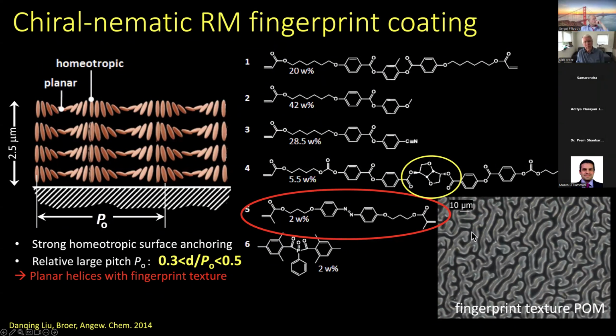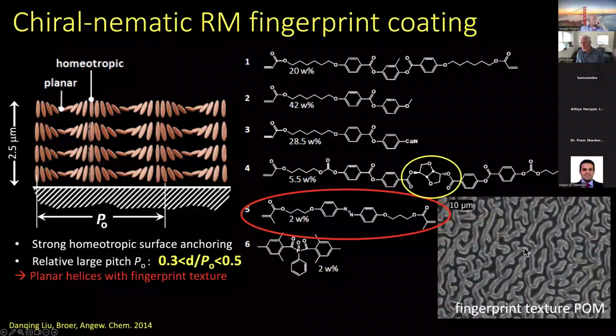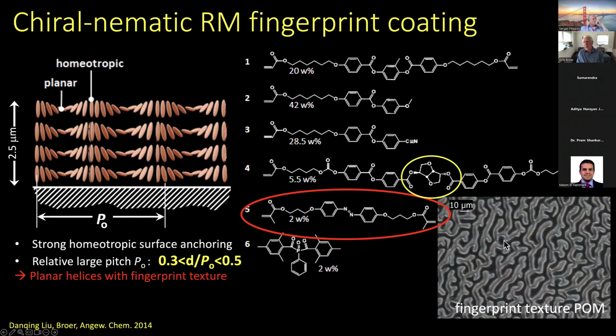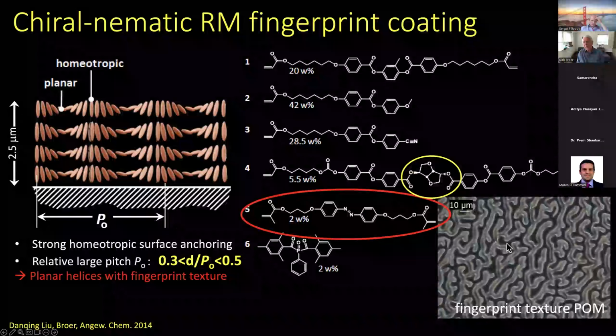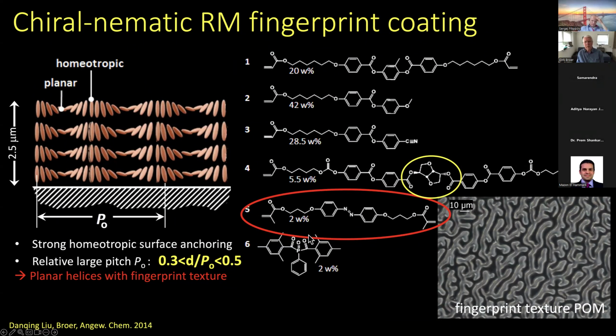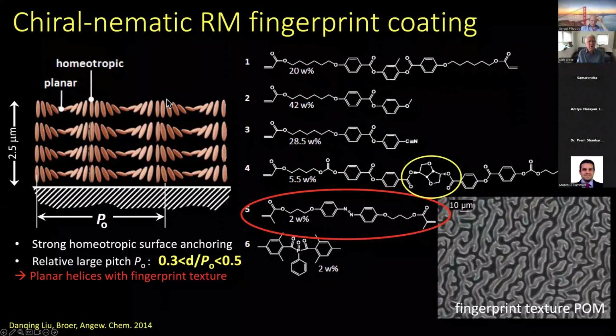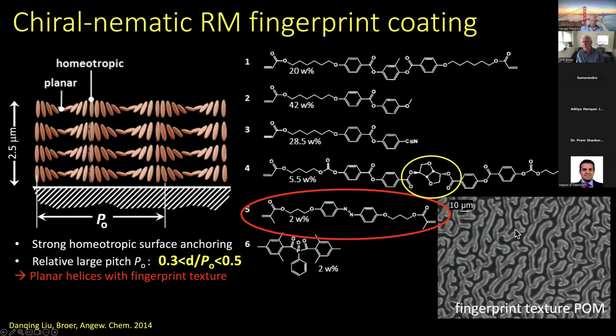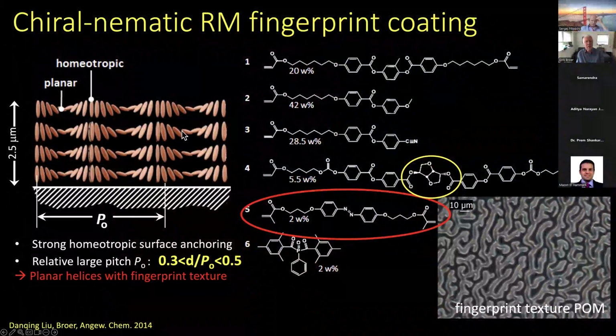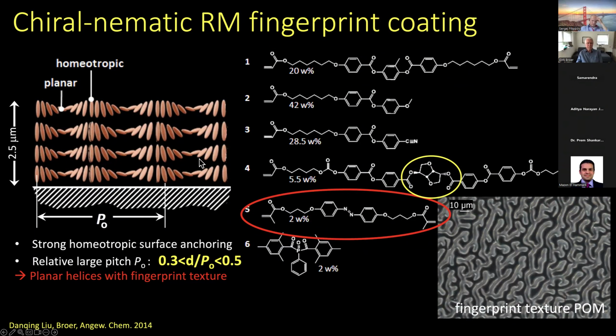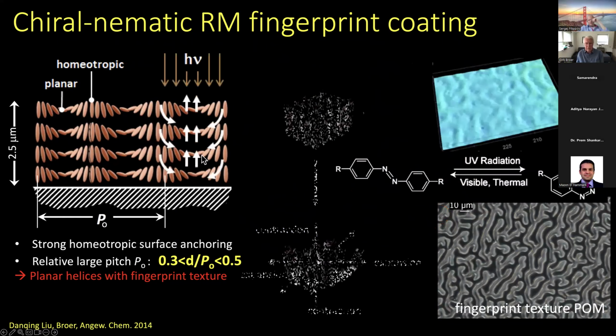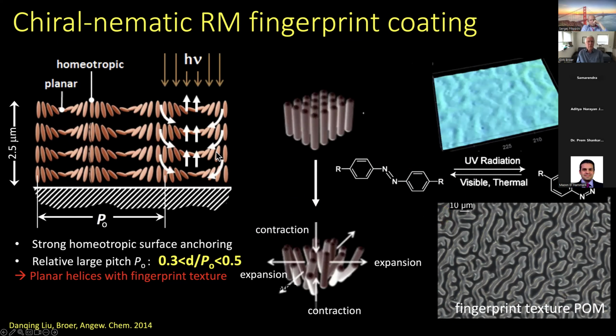If you look through the optical microscope, you see structures like this. This is also why they are called fingerprints. In the black areas, the molecules are perpendicular to the surface. In the bright areas, they are different. So this is more or less the position of the helix. In the bright areas, they are in the more planar state. And you can now imagine, if you expose with UV light and change the order parameter, that the planar areas want to expand, and the perpendicular areas want to shrink, right?